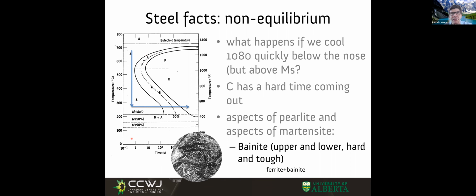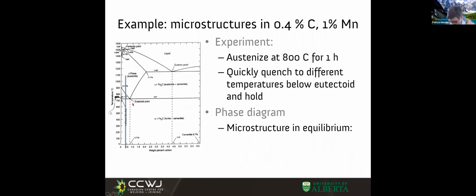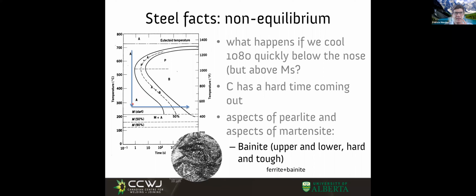But what happens in welding most of the time is none of those. The structure that relates to welding the most would be reproduced in this experiment as follows: let's quench in our salt bath, but let's quench to about 275 degrees—this height. So I quench very fast, but I don't reach the start of martensite. I do not transform to martensite, but I hold it.